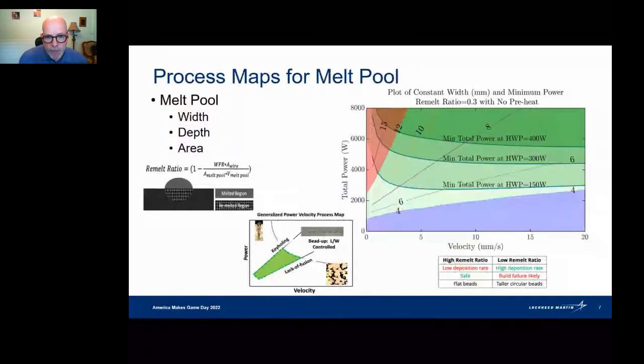One of the first things we did, I mentioned process maps. What Jack Buth and his team learned initially was that we needed a process window within which we could have a reliable deposition and something that would deliver a good quality deposition in each different bead that was laid. So it's important to deliver the right amount of energy into the melt pool.